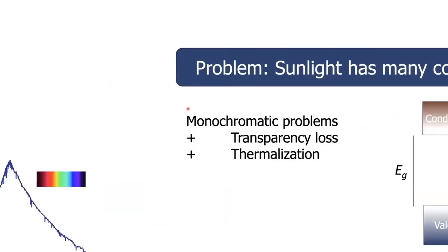The main problem of converting the sunlight is that sunlight has too many colors. So this is the photon flux as a function of photon energy arriving just above our atmosphere. So if you were a satellite, this is what you would see. It's just a little cleaner for discussion today. So the problem is we have all of the monochromatic problems, which is to say the radiative emission, but we add two extra problems to it. These are transparency and thermalization.